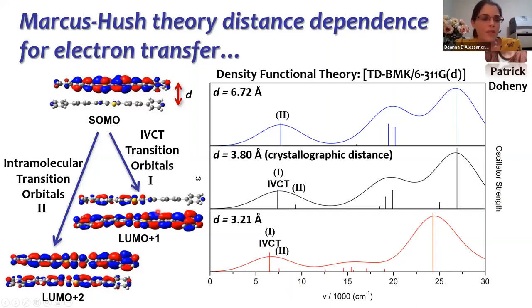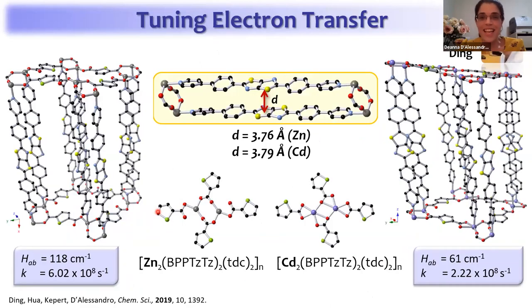What really struck me was just how subtle this can be. Although nature uses intervalence charge transfer to good effect, and it is indeed very subtle in nature, if we just change the distance between these ligands a little bit, and this is outside experimental error, and we move from a cadmium to a zinc, you can see here that the HAB for the cadmium system, which has an ever so slightly larger cofacial distance, is about half of that in the zinc system. And this also changes the rate constant for electron transfer.